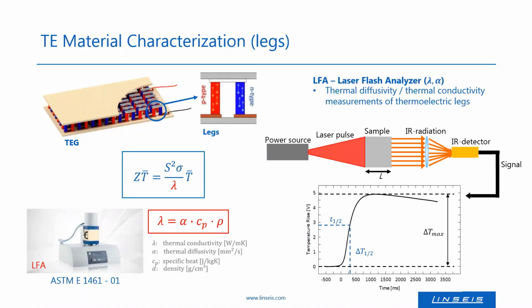The LFA measures the thermal transport properties, so the thermal conductivity more or less indirectly. The laser flash method is a standardized technique which uses a light source. It is either a xenon lamp or a laser. And this power source shoots a short high energy pulse to one side of the sample. The sample absorbs the energy, and a part of the energy is also emitted on the rear side of the sample. And this infrared radiation is collected by an infrared detector. So in the end, one obtains a temperature rise curve with time, which looks similar to this one here.